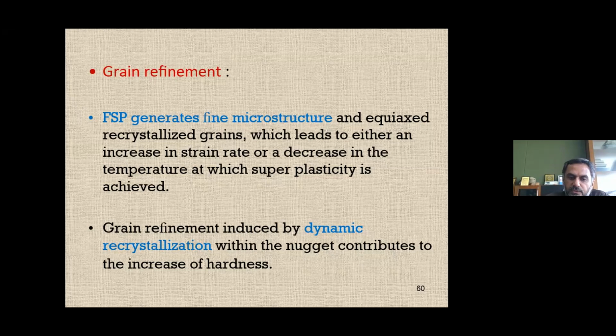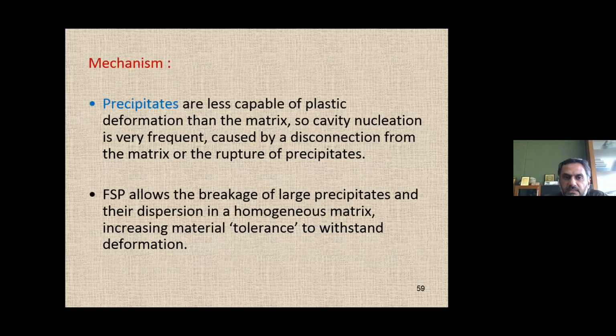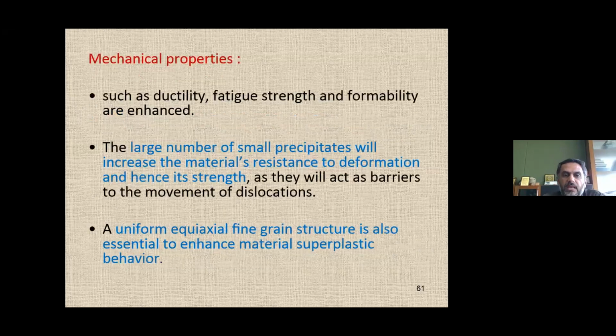Then the nugget contributes to an increase in hardness. So this is another mechanism, the grain refinement and the precipitates distribution. So mechanical properties such as ductility, fatigue, formability, those things also get enhanced with the help of FSP, right? Why? Because those large amounts of precipitates that you have in the matrix, right? They also get deformed, they reduce their size, and they act as a barrier to dislocation motion. And you have a uniform equiaxed fine grain structure, right? Which also helps you to enhance the superplastic behavior of the material.